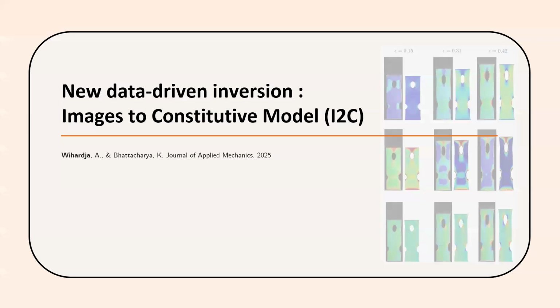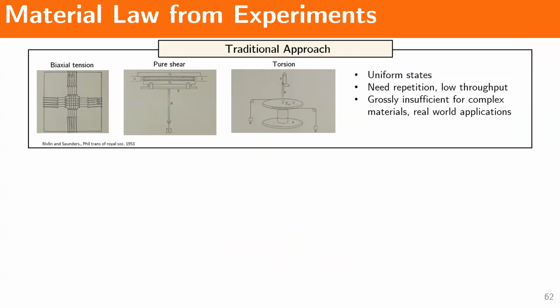So this leads us to the second part of the project, where we try to create a new inversion technique called image to constitutive model, where we can get constitutive relations directly from raw images, because we really want to leverage all the underlying data in those raw experimental images. In general, it is a little hard to get constitutive relations directly from experimental data. The reason is our constitutive law is usually a relationship between the stress and the strain, so the stress and strain are not directly measurable in an experiment. You never directly measure that.